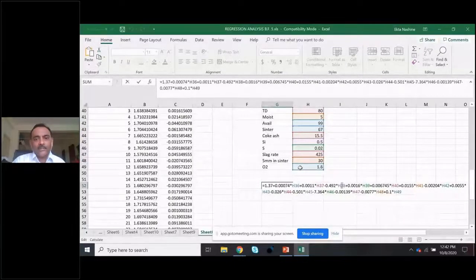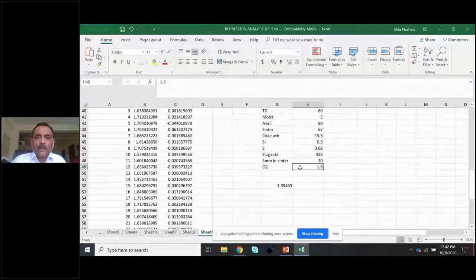In the comparative data of international standard you have seen, that's why they are able to get great productivities. So we are generating data and we are able to get the productivity also. I'm just putting some values for the example. Let's say my tapping duration is 80%. 80% means out of the 24-hour time, 80% of the time my furnace tap hole is open, from which I am able to remove metal and slag.